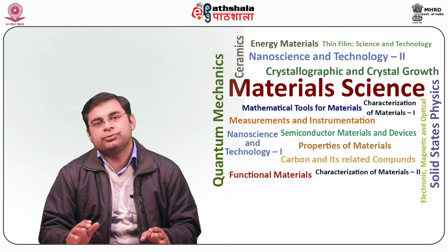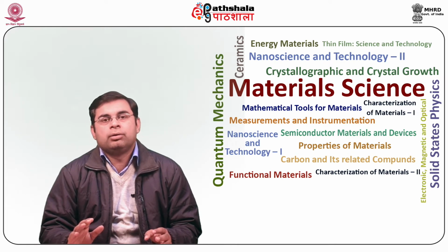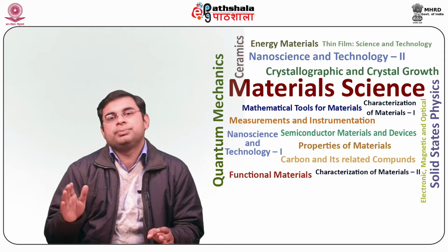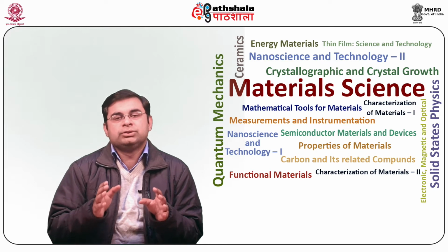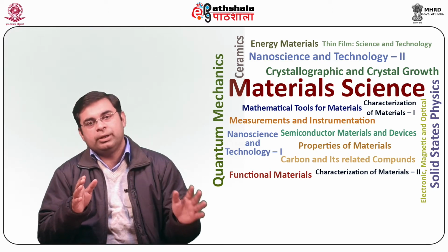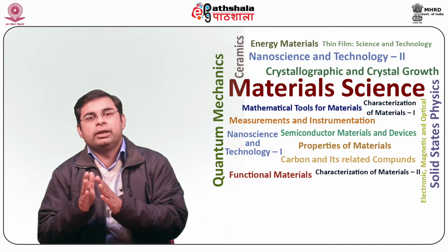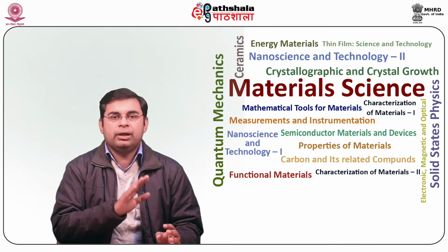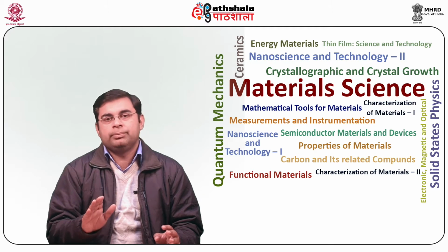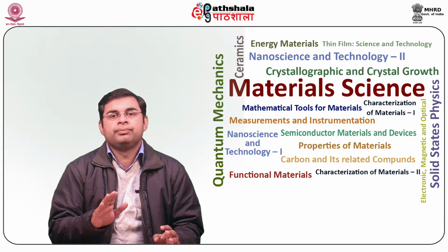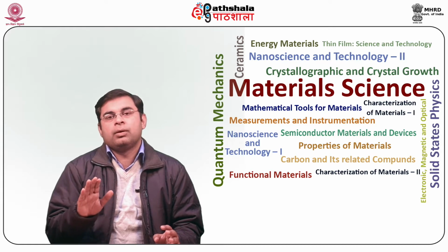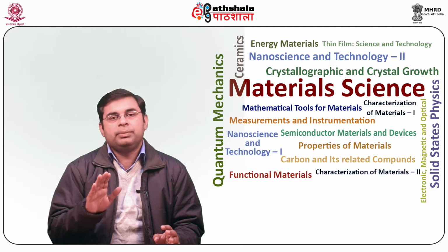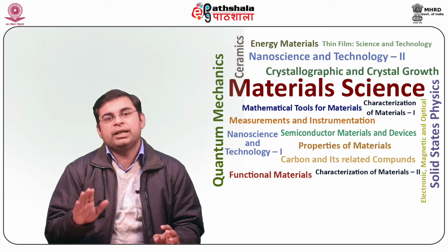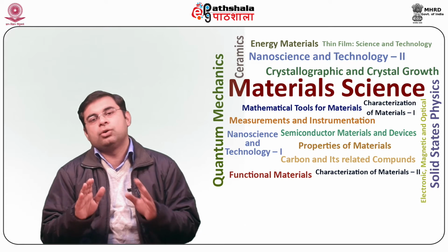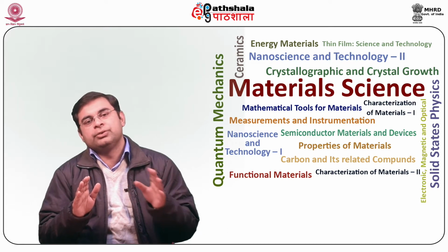When the metal semiconductor interface is formed, this energy offset phi Bn naught, also known as the n-type Schottky barrier height, causes a potential energy barrier which acts as a rectifier, such that electrons can readily flow from semiconductor to metal, while electron flow in the opposite direction is difficult. When the semiconductor in contact with the metal is doped p-type, the energy gap between the Fermi level and the VBM, marked as phi Bp naught, becomes the energy barrier, that is the p-type Schottky barrier height, that governs the whole transport across the metal semiconductor interface.